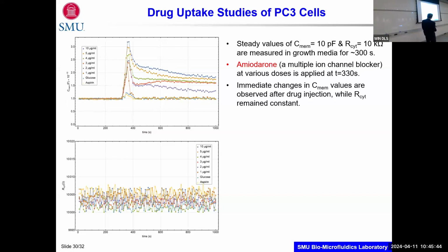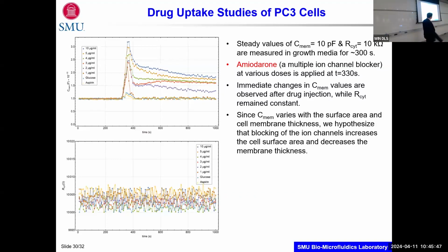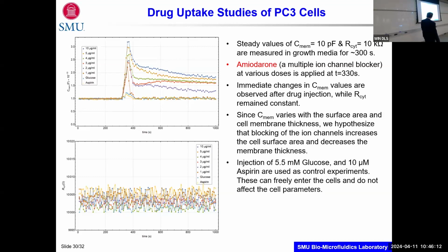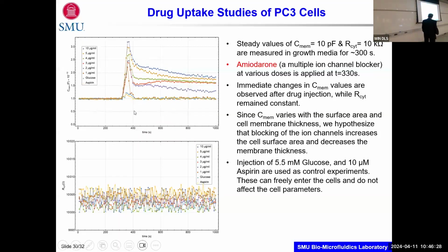So we believe that these changes are due to the change in the surface area and the cell membrane thickness, and how these medicines are being internalized on the cell membrane. So as the ion channels are closed, I expected the cytoplasm resistance to remain the same, and we are seeing that. So that makes sense, at least to me as an engineer. So in order to do a negative control, we used glucose and aspirin, which apparently can get in and out of the cell very easily, and their effects are these little bumps, much smaller than the others.